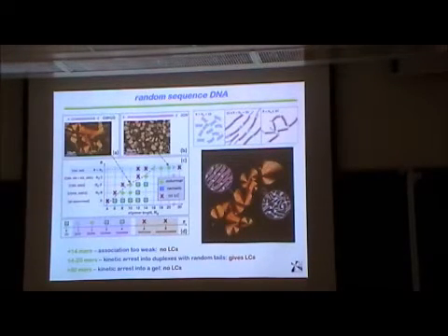So the solution becomes basically filled with these things that look like this. Half of them are complementary, and then they have these tails sticking out. The tails make these aggregates attractive. So you get end-to-end attraction, which is the basic requirement for getting liquid crystals. So you have sections of strong linking, which is the red, and then sections of weak linking, which is the blue. That makes liquid crystal ordering.